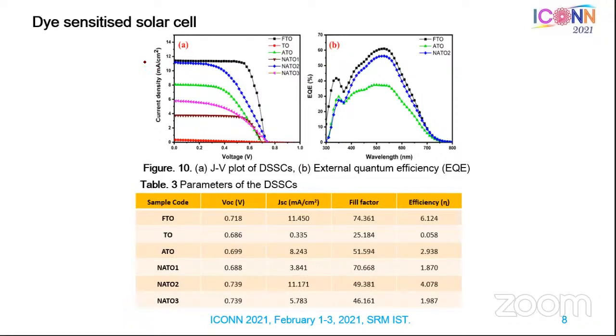We have prepared dye-sensitized solar cells with the as-prepared thin films. These are the IV measurements, and these are the external quantum efficiency. So coming to the JV plot, we have taken the FTO film as reference. For FTO film, the efficiency is 6.1. This is the highest efficiency.